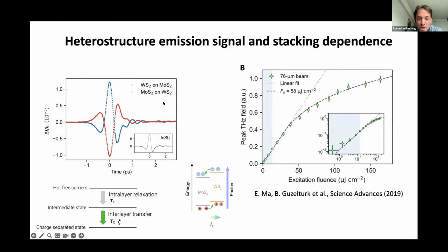I don't have time to really talk in detail about all of the results of this measurement, but I will just say that through some more detailed fitting, one can try to extract mechanistic information about these currents. You can try to separate out the timescales for relaxation processes of hot carriers to the bottom of the band from an interlayer charge transfer time. You can extract quantitative information on the magnitudes, and we extract direct quantitative measurements of the efficiency of this process.